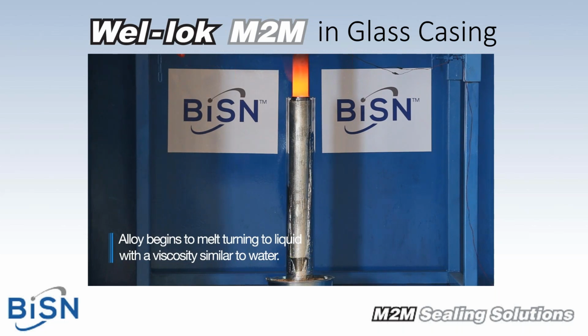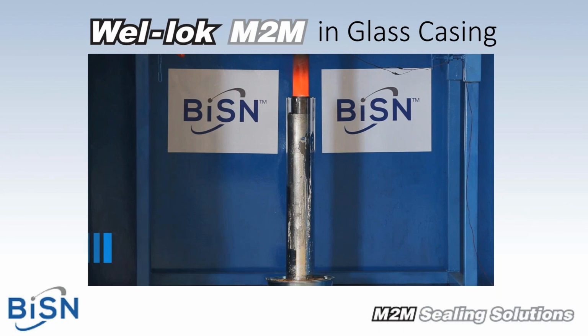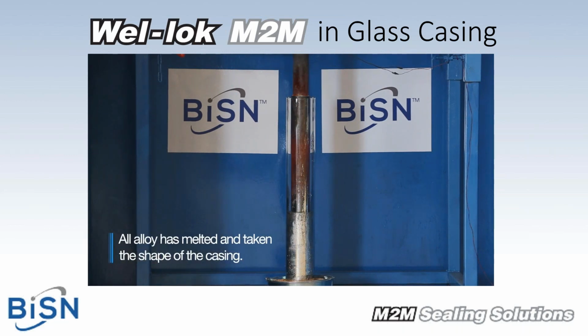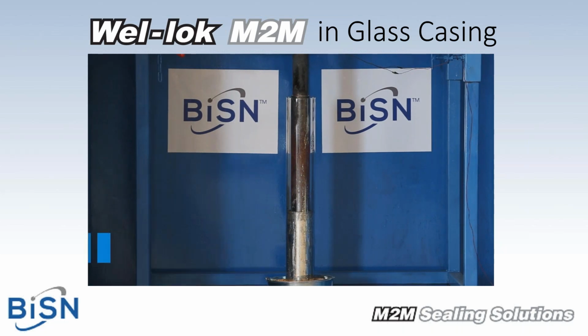It forms its own base, basically because it's eutectic, so it has a very sharp melting and freezing point. 1 C difference or a couple of degrees F difference in temperature becomes a liquid or a solid. As you can see, very, very quick reaction. A couple of minutes, we can now melt approximately 10,000 kilos or 20,000 pounds of this alloy in less than an hour downhole. So very simple, but very effective.